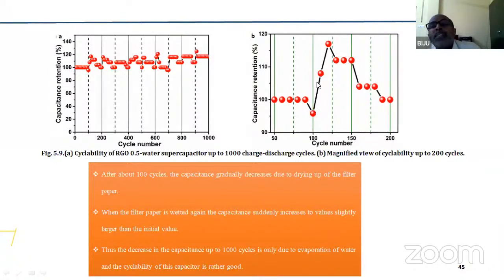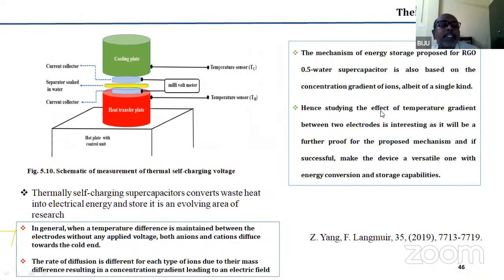But when we wet the supercapacitor again, what we obtained is again a regaining of charge. Actually, its capacitance was more than 100% compared to the previous value when it was wet, and again it gradually decreased as the water was drying. Now, this is the experiment that we did with a hot plate, with one hot electrode and the other cold